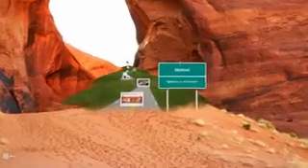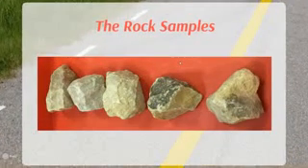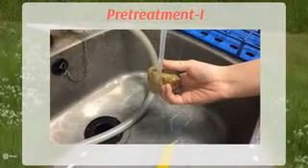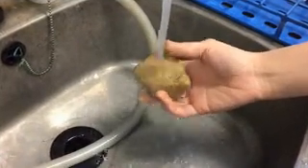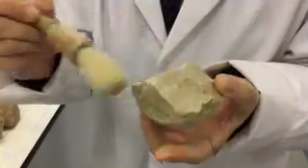The following part is the method we used in this experiment. First of all, the rocks we chose were polished sandy limestone. 5 classes were chosen according to the similarity in shape and size. To calculate porosity, the 5 classes were initially washed by running water to remove the originally existing salts. After being oven dried at 105 degrees Celsius for 8 hours, the surface residues were swept.